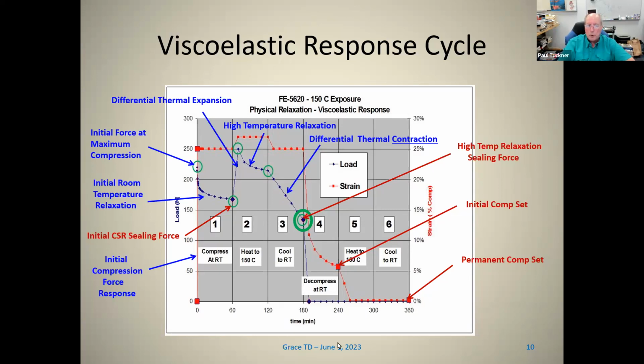In the first part, if you take a specimen and compress it at room temperature, it's a simple compression up to a given point of strain. If you hold it at that point of strain, you see the relaxation curve - over a period of 60 minutes you'd get to this point. So after 60 minutes of relaxation, that value is the initial value used if you're doing discrete CSR testing.